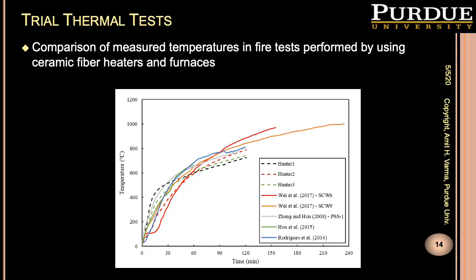Without getting into too many details, here I'm showing you the results of our trial thermal tests. What I'm showing you here are temperature time curves on the surface of the steel plates of the composite plate shear walls. You'll notice that the dotted lines are coming from the ceramic fiber radiant heaters that we used in our laboratory. And the solid lines, for at least two of them, are coming from the tests conducted by Wei et al. on the composite plate shear walls.